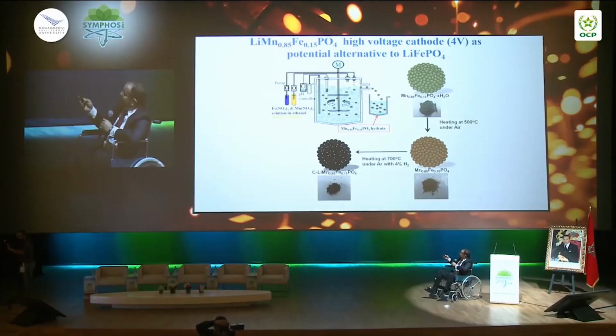This is an example that shows the co-precipitation. Basically you take the precursors, mostly nitrate, which are very low cost, and then you add phosphoric acid, and you create a chelating agent and co-precipitating agent, and you co-precipitate your material, and then you treat it with a carbon coating, and you end up with a black type powder that is carbon-coated manganese phosphate. It's very simple, as long as you control the conditions. There is an art of parameters that need to be controlled to get where you want.